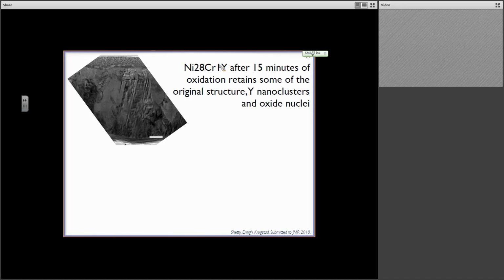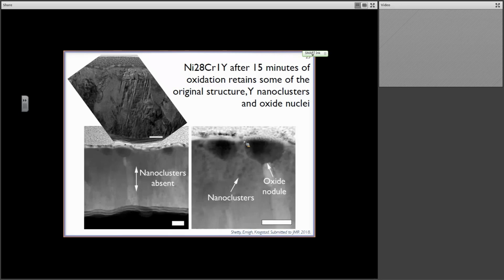And so this is just the nickel chrome, no aluminum here, but even after 15 minutes, the interesting thing is, rather than forming these big bamboo-like structures where the grains are all the way through, after 15 minutes of oxidation, some of this columnar structure actually is still retained. All right? And we again see these little nanoclusters. The nanoclusters form on the top and bottom of our thin film, but they're not found in the center of the film.